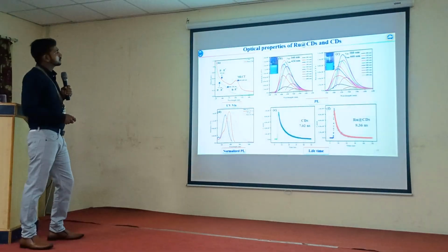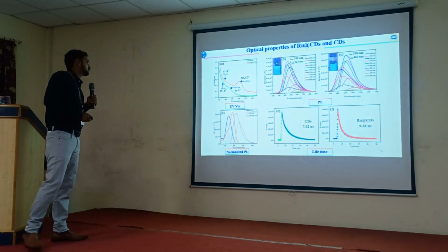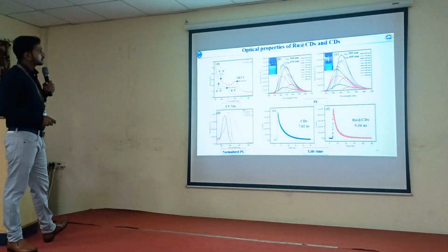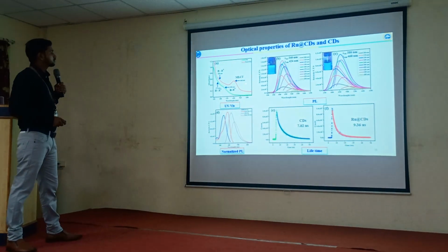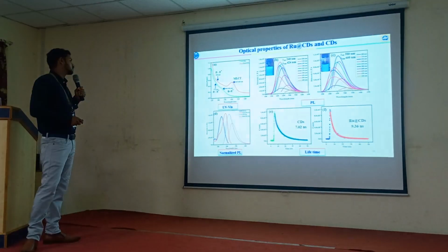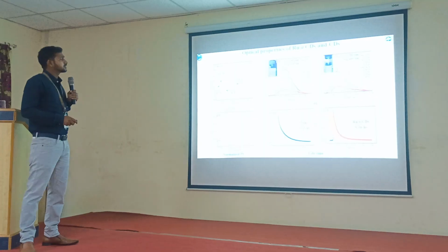And the ruthenium carrying carbon dots also express two different absorption peaks, which correspond to the pi to pi star transition, with a peak position at 448 nanometers, which confirms the metal to ligand charge transfer spectra and further confirms the existence of ruthenium in the matrix of carbon dots. Figure B represents the photoluminescence spectra of carbon dots with excitation dependent emission behavior with a maximum emission wavelength of 424 nanometers, and figure C represents the ruthenium carrying carbon dots with a maximum emission of 460 nanometers.